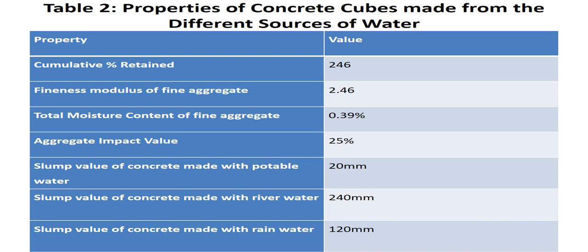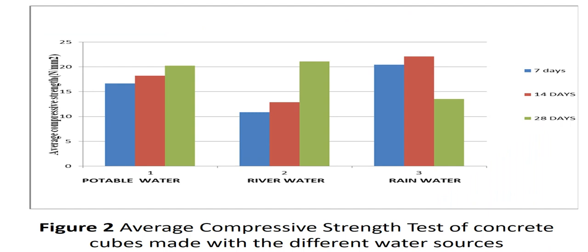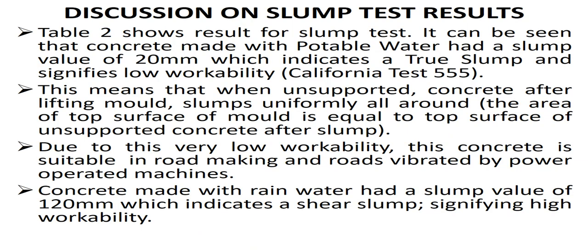Table 2 shows the properties of concrete cubes made from different sources of water. Figure 2 shows average compressive strength test of concrete cubes made with different water sources. Discussion on slump test results. Table 2 shows result for slump test. It can be seen that concrete made with potable water had a slump value of 20 mm, which indicates a true slump and signifies low workability.